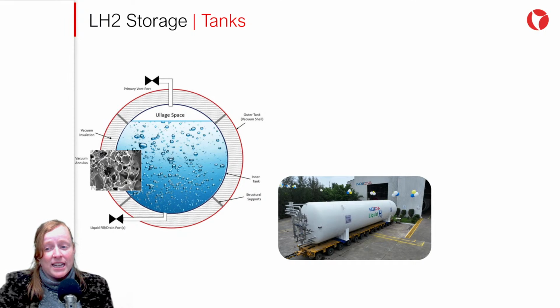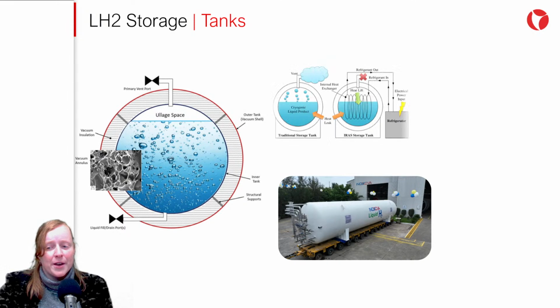Boil-off gas is an inevitable result of LH2 storage. A certain percentage of liquid hydrogen will eventually enter the gas phase, depending on factors such as wall material, quality of the insulation, and the surface to volume ratio of the container. Typical boil-off values range between 0.1% per day for larger spheres and up to 1% per day for smaller tanks. The most common design does not include active devices to prevent boil-off, although integrated refrigeration and storage systems have been developed aimed at maintaining the stored liquid in a state of zero evaporation.